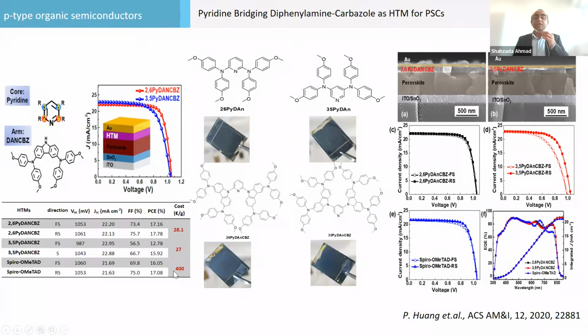But the significant part was the cost. The spiro is almost €400 per gram, and this we can synthesize at €30 per gram. The cost is very reduced because it's a very simple synthesis. And also we believe that this pyridine core will also interact with the uncoordinated lead and will increase the stability.